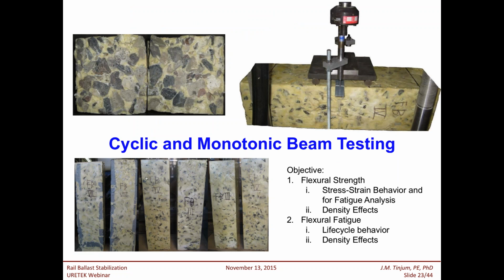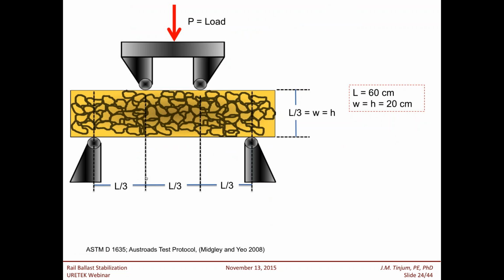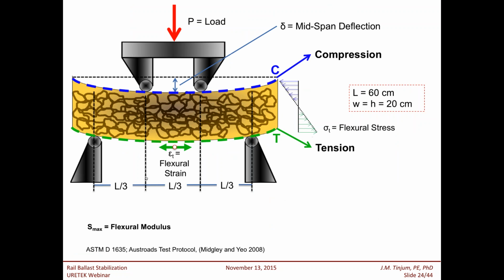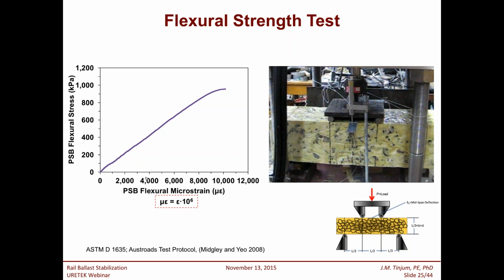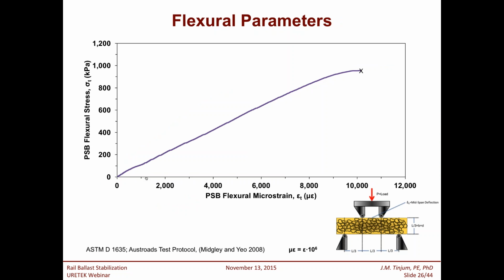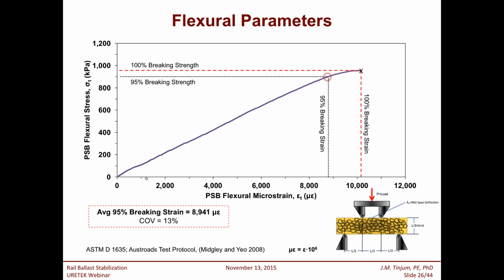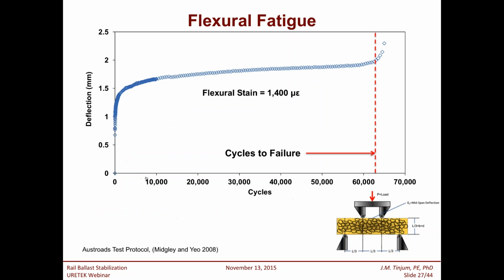Cyclic and monotonic beam testing. We have 3-point beam tests, and this goes more to the flexural strength and the repeated dynamic loads to the system. Those have been measured. Flexural strength tests will get at the breaking strength, to get the flexural parameters of the polyurethane stabilized ballast. Flexural fatigue, how many cycles it takes to fail the material, also goes to the longevity of the material.